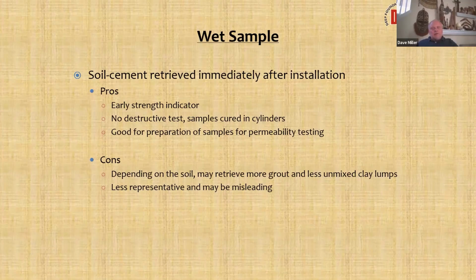Like I said, you can test it at 3 or 7 days. You would never be able to core it that soon to test it. It's a non-destructive test. You're not coring into your wall. You're just grabbing a sample while it's still fluid, so the material can close up. And it's one of the better ways to get a sample for permeability testing, in my opinion.